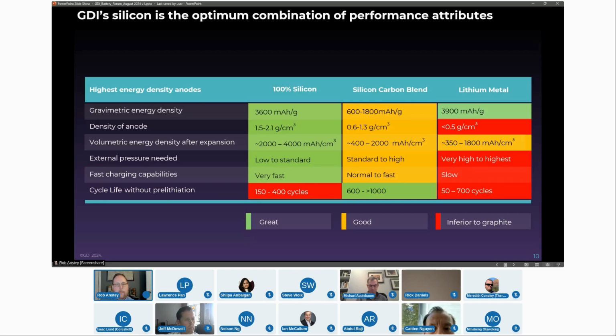Now, silicon carbon expands the least, silicon expands the second least, and lithium will expand forever unless you put megapascals of compression on it. So once you actually dig into the numbers, even if we give everyone the benefit of the doubt of giving them all the energy, when you multiply it by the density of the anode, and then you multiply it by the average areal loadings that they're capable of demonstrating with third-party data, and you need third-party data, unfortunately.